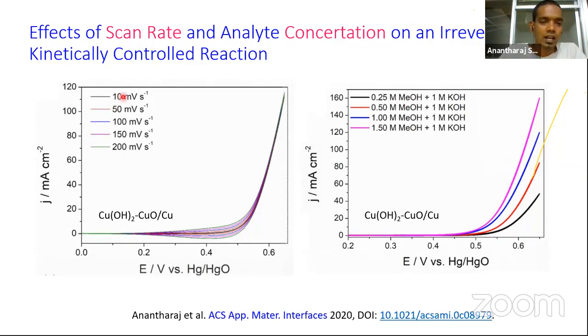So in this case, I have increased the scan rate, that is the speed of the potential ramp that I have applied in this potential window, from 10 millivolt to 200 millivolt as 10, 50, 100, 150 and 200 millivolt. You can see there is no increase in current density. So this is a peculiar characteristic of a completely irreversible kinetically controlled reaction, and this can be witnessed with all cases of gas evolution reaction.